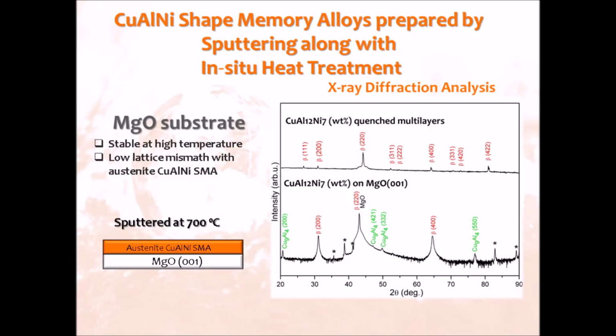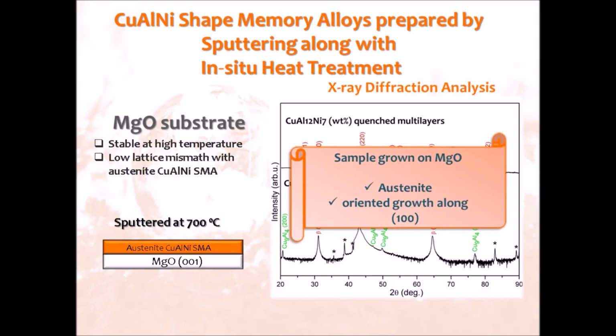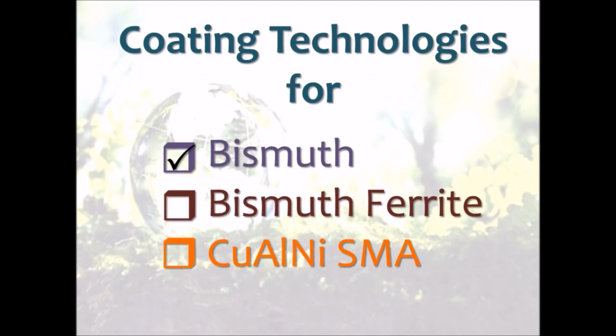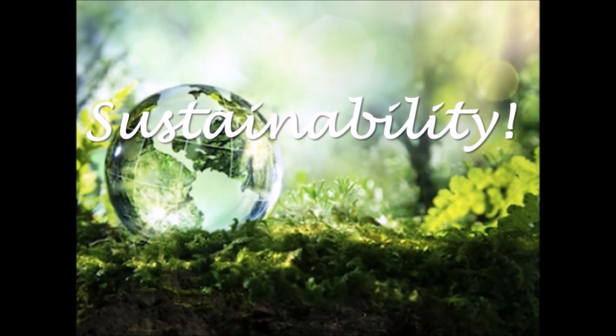Moreover, it can be seen that the low lattice mismatch favored the oriented growth of the sample along 100 direction due to presence of strong 200 and 400 peaks in the XRD results. Throughout all these studies, it was shown that bismuth, bismuth ferrite and copper aluminum nickel shape memory alloys could be synthesized by using coating technologies as sustainable materials for novel applications.